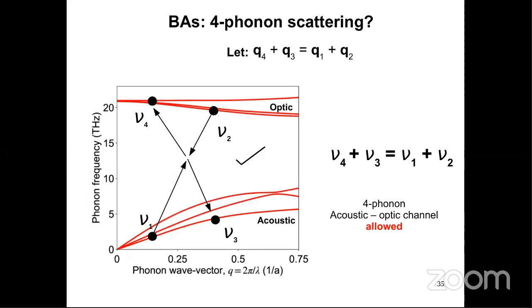What about higher order scattering involving more than 3 phonons? So clearly, you can see from this picture that if you add 1 more phonon to the mix, you can satisfy both momentum and energy conservation simultaneously. So at least from the constraints perspective, the 4-phonon acoustic-optic channel is allowed. But typically, scattering events involving a large number of phonons are a higher order process in perturbation theory, and the strength of these higher order processes is expected to be weak.